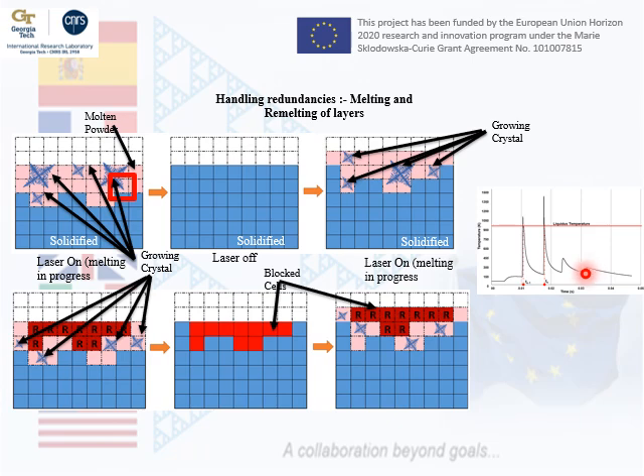So we are going to track back the time of each cell, and we are going to set the point at which solidification is most likely. So this is the point of certain solidification, right? We don't know whether this cell is going to nucleate or not, because we also need to consider that the cells have different probabilities of nucleation, right? So we don't know whether this cell is going to nucleate or not, but we know that when this cell nucleates or solidifies, it can only happen after this time, right?